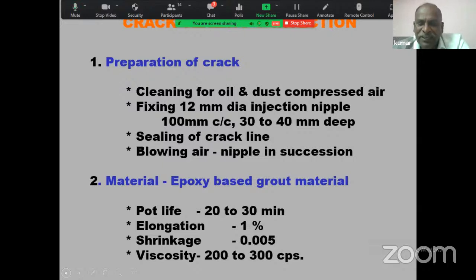Then after that, you have to go for epoxy-based grout material. Why are we going for epoxy-based grout material? Epoxy has very good adhesion and very good mechanical strength, almost equivalent to your concrete. It has more elasticity, so it will not be that brittle. So we have to select a low molecular weight epoxy as the grout material.